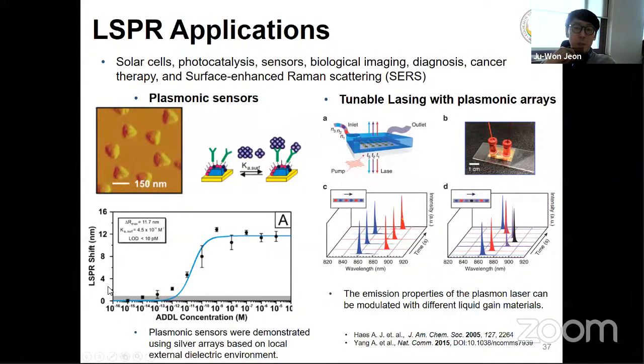So based on the LSPR peak shift, we can identify the existence of the specific chemicals. And to some degree, we can also know the concentration of the specific chemicals. Another example is the tunable lasing system with the gold nano array. By using the gold nano array with several different liquid gains, it was possible to tune the lattice plasmon resonance and also modulate the emission property of the laser. So we can control the color just by providing the medium.